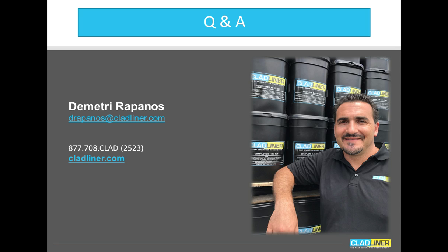Does the product shrink during or after the curing process? There is very little shrinkage in the product because even though it has a waterborne epoxy, the water that comes off the curing of the epoxy actually gets sucked up by the cement, so there's very little shrinkage.